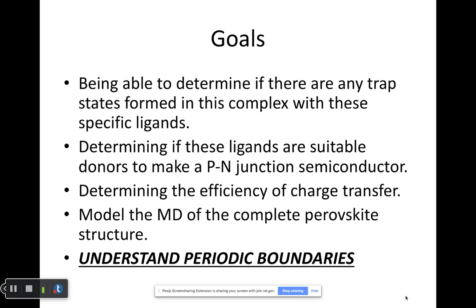So technically you said in the very first sentence that you wanted to see whether you will have a trap state due to the ligand, right? But even if you have no ligands at all, your surface, due to the surface reconstruction, because again it's lacking the atoms which should be in a bulk structure, this surface reconstruction or these surface defects might lead to trap states as well. So I would say you probably need to check that you don't have trap states due to the surface, and then maybe look at your ligands.